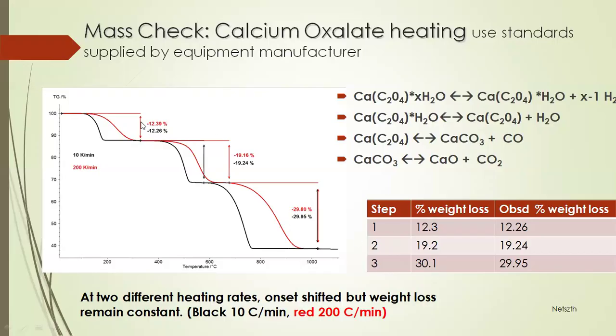Now, for each step, the weight loss is known. For the first step, the calculated weight loss is around 12.3, and TG measures the weight loss as 12.26. You can see how accurate our TGA measurements could be. The second weight loss is known for the second step, which is around 19.2, and TGA measures it at 19.24. Similarly for the third step also.